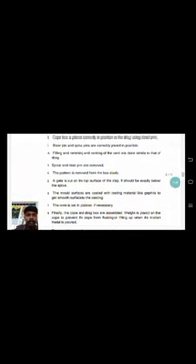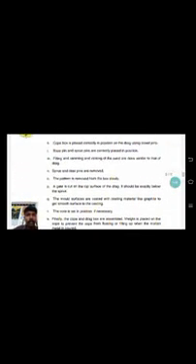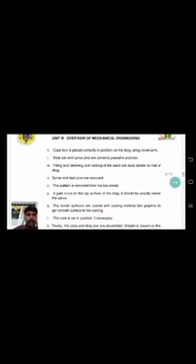Next, the cope box is placed correctly in position over the drag using dowel pins. Next, riser pin and sprue pin are correctly placed in the required positions. Then filling, ramming, and venting of the sand are done similar to the drag. Then sprue and riser pins are removed accordingly. The pattern is removed from the box slowly.